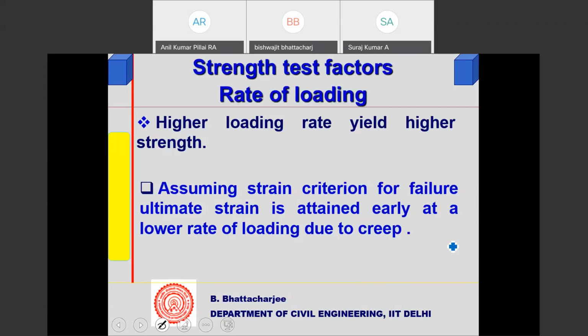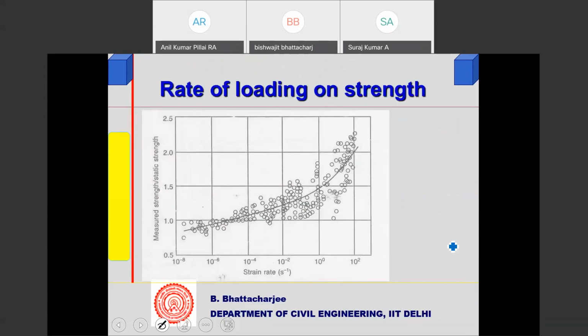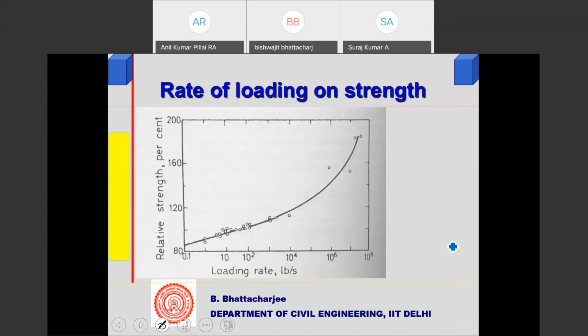Now strength test is important, which I didn't cover so far. See, as we test strength, our rate of loading is very important. And I find that many test laboratories don't bother. That's why I've kept it here. So higher loading rate gives higher strength. Now IS code has standardized it to 14 MPa per minute. So rate of load, strain rate, as you increase it, measured static strength increases. So basically this is rate of loading. This is from an old book. So pound per second was used, and you find that strength increases because of crack propagation time. So these are the issues.